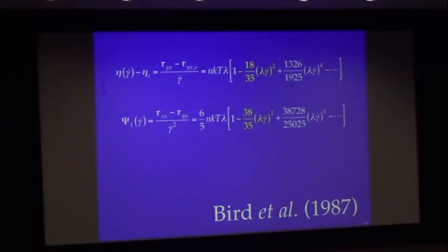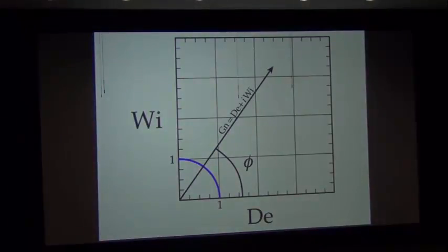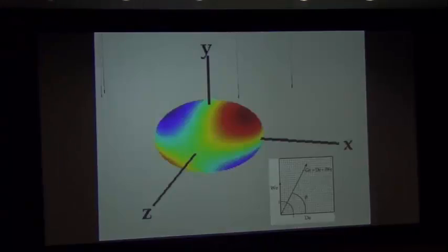We can talk about the first normal stress difference, though, also shear thinning as it should be, and the second normal stress difference in steady shear flow, molecular theory gives you 0. So that's important to remember. This is not quite as good as the continuum approach, but it is connecting us with molecular structure. Now, if we look at the generalized Newtonian model, this is steady simple shear. We will now deepen our understanding of shear thinning by just looking at that orientation distribution function.